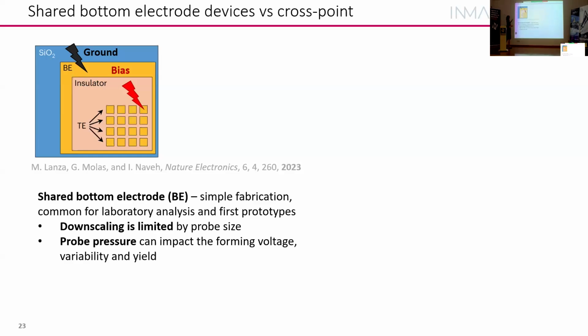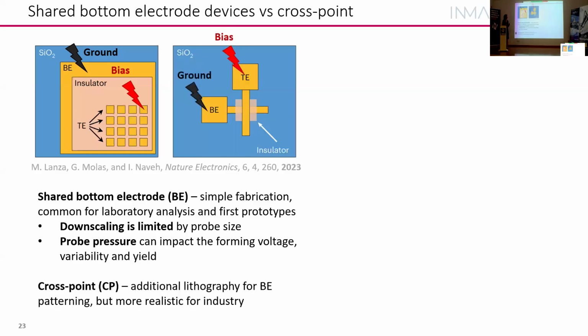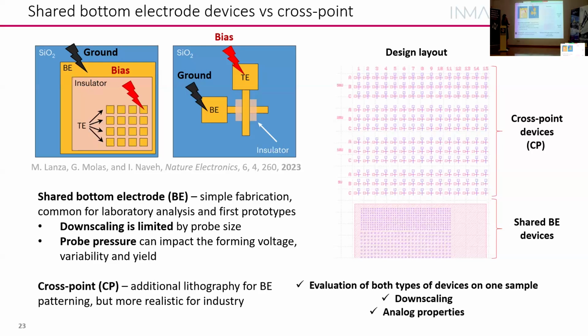In a real device, what you will have is that the bottom electrode is also patterned. Here we were really limited for the downscaling to the size of our tip that we could contact. And you can damage the electrode, you can scratch it, you can really touch the film sometimes. So we wanted to do better, and to do better, what we did is to do these cross point electrodes. So then we contact far from the electrode, we do not damage it, and we're really measuring smaller sizes of devices here. We could go really downscaling. This is our design layout.